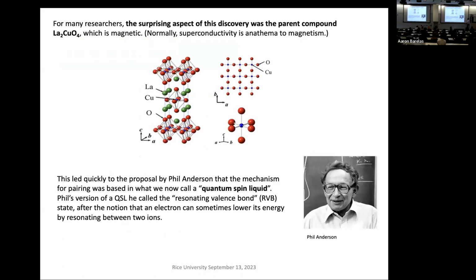For many researchers, the surprising aspect of this discovery was that the parent compound, a cuprate, is magnetic. Normally, superconductivity is anathema to magnetism, so to see superconductivity in a material that has copper 2+, which is a magnetic ion, was surprising. This led quickly to the proposal by Phil Anderson that the mechanism for pairing was based in what we now call a quantum spin liquid. Phil's version of the quantum spin liquid he called the resonating valence bond model, after the notion that an electron can sometimes lower its energy by resonating or hopping between two ions, similar to the popular explanation of covalent bonding that was supported by Linus Pauling.